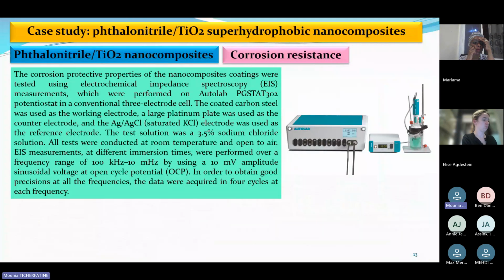The corrosion protective properties of the nanocomposite coating were tested using electrochemical impedance spectroscopy, EIS, measurements, which were performed on a potentiostat in a conventional 3-electrode cell. These measurements were taken at different immersion times and were performed over a frequency range of 100 kHz to 10 mHz.